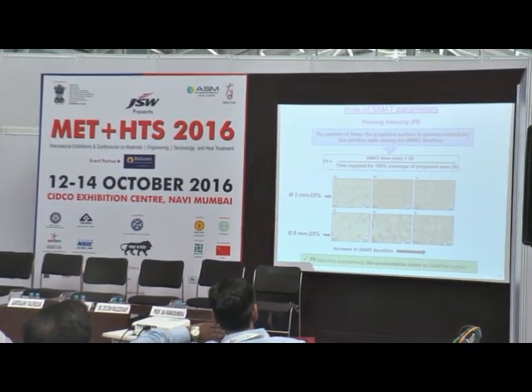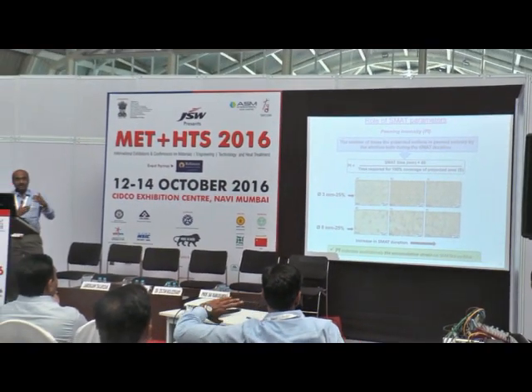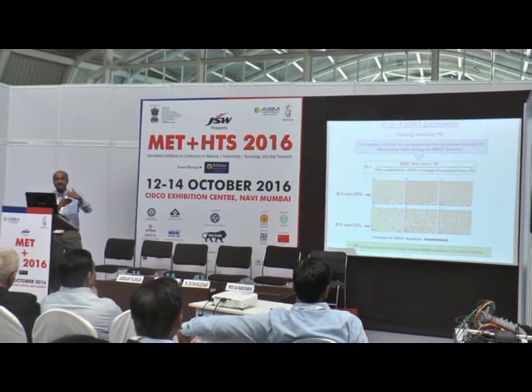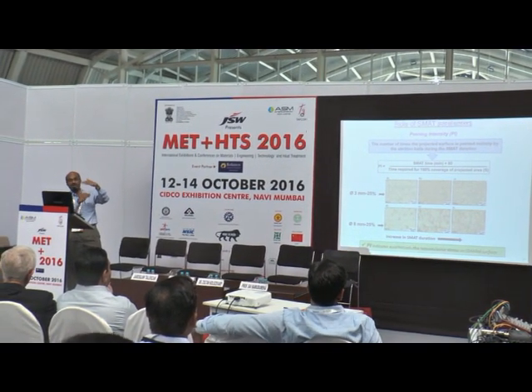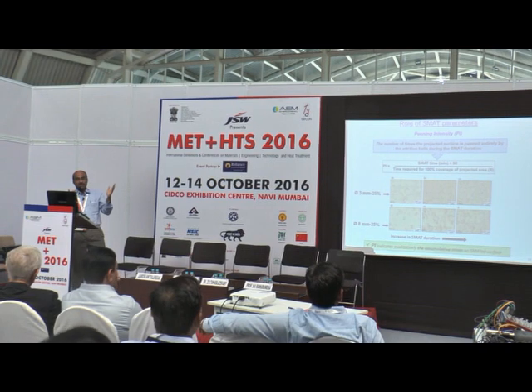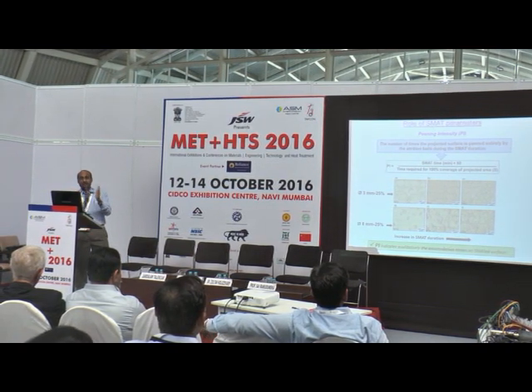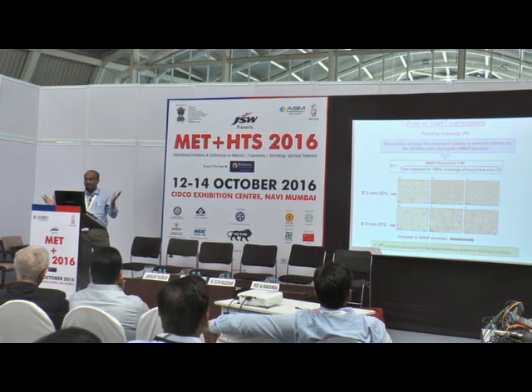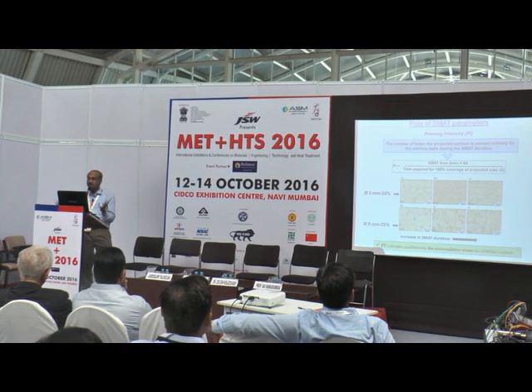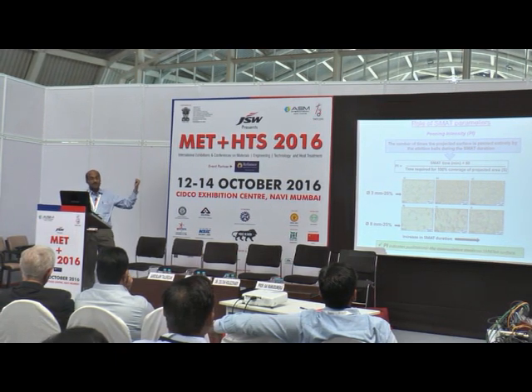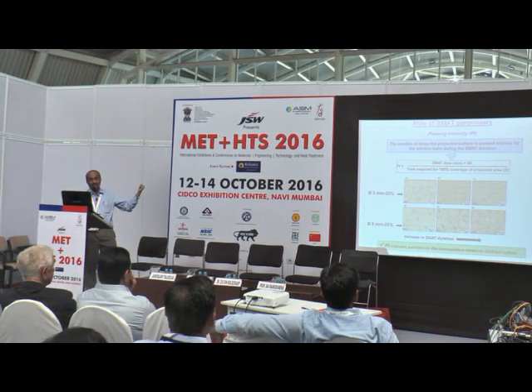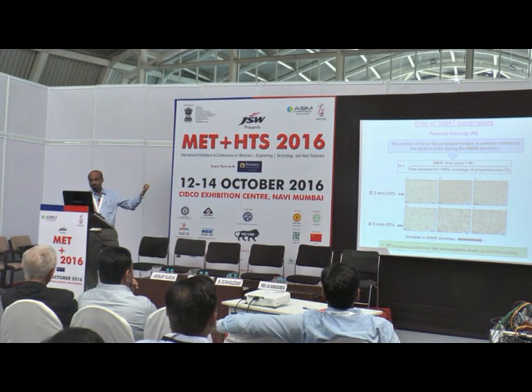Now how do you explain it? There are plenty of things. I have a different impact if I change the gap between the specimen surface and the bottom plate. The number of balls is another variable. Then SMAT duration is another variable. So I have plenty of variables. How can I explain all those variables with a single term? That is by using peening intensity. That is a major contribution by us to this particular phenomenon.